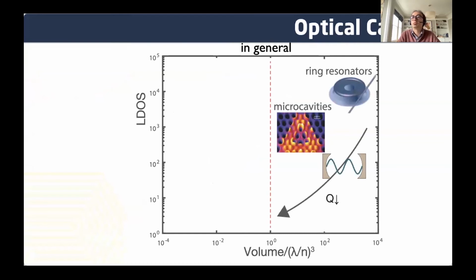How do we do that? Well, traditionally, this is done with optical cavities by placing an emitter between two mirrors, in a ring resonator and so on. So in this plot, I'm plotting the size of the optical cavity versus the Purcell enhancement, so what I call the local density of states. So you see that when I make the resonator smaller and smaller, what happens is that we lose Q value. So in some ways, we trap the light for less and less time in this resonator. So we lose the temporal confinement. And therefore, often this was thought to be a bad way. So usually you want to go to larger sizes to get a stronger effect.